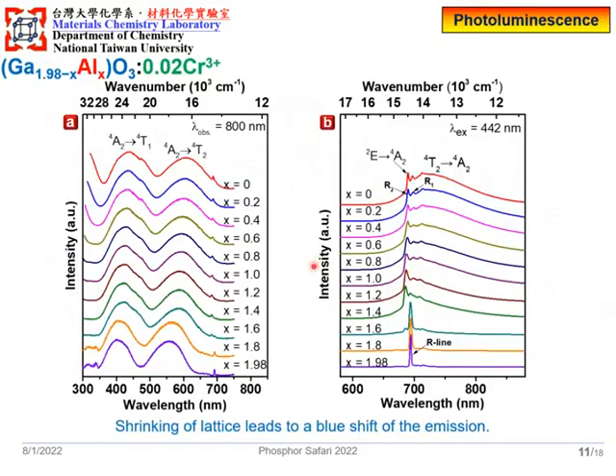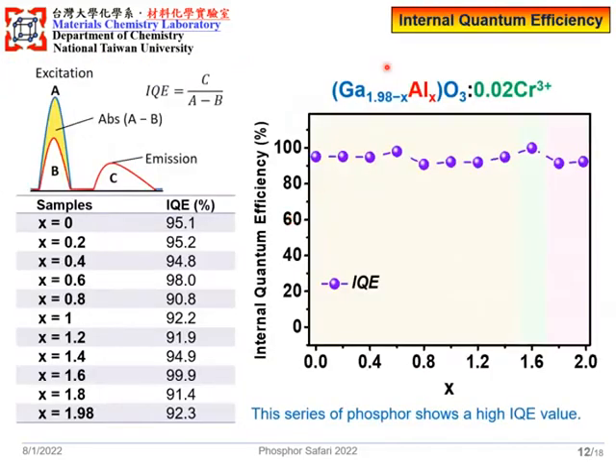From the room temperature PL measurement, we can find out that the spectrum blue shifts, and it results from the shrinkage of the lattice and the enhanced crystal field strength of the structure. We also measure the internal quantum efficiency to evaluate the potential of this series of phosphors. We can find out that all samples obtain quite high IQE performance.